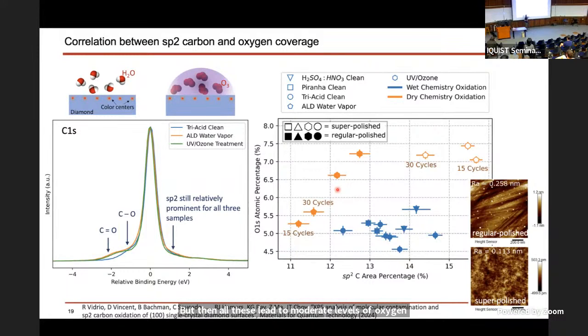And then we tried a couple of dry oxidation approaches. One is just UV ozone, and the other uses an atomic layer deposition tool where we send water pulses at some elevated temperature, and that seems to do a good job of oxidizing the diamond surface. And there we see a good relationship between the amount of oxygen that you find and the graphitization.